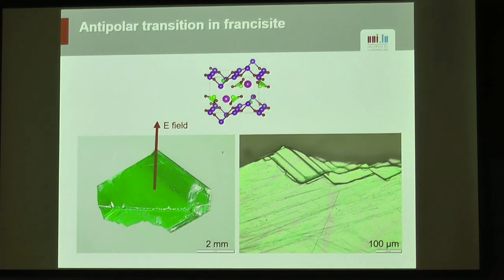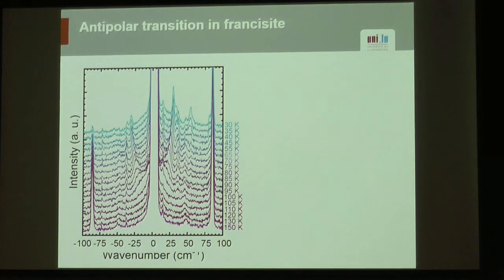But going back to my original motivation, I mentioned that this was a good candidate for a soft mode-driven antipolar or antiferroelectric transition. So I want to go now to the spectroscopy experiment. So this is the phase transition at 115K, as seen in Raman spectroscopy. So essentially, the structure is complex, so you have many phonons, but what we want to focus on is this one here at low frequency, and it exhibits a really nice soft mode behavior. This is the lowest temperatures, goes to zero here, and disappears, is not visible above TC.